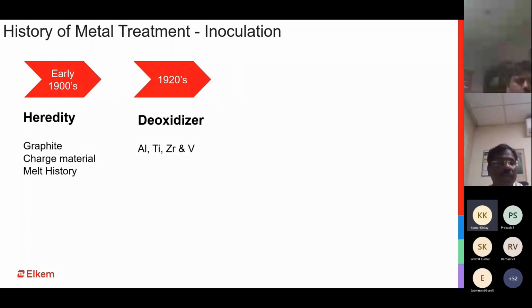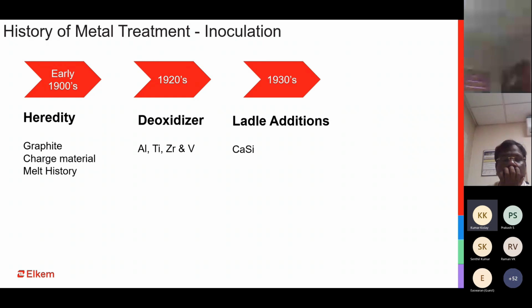Things changed a bit in the 1920s or so, when we moved about 15, 20 years, probably coinciding with the First World War, when the industry wanted the metal casting pieces to be more efficient, more strong, better in strength, better in soundness. And that is when deoxidation as a concept was brought into the cast iron industry. The major elements which were used as deoxidizers were aluminum, titanium, zirconium, and vanadium. So these were the main elements. Some of these elements still are used till today. So it has been 100 years since we started or discovered the use of these elements for the inoculation, and some of it is still there today in the inoculating concept.